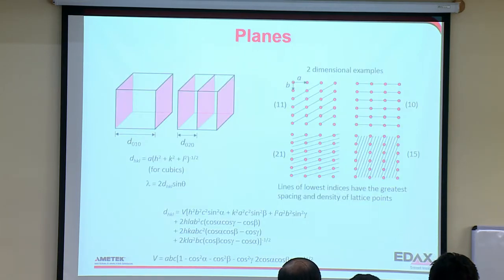So a note about planes. D-spacing is somewhat important in EBSD, although not critical. And just to show you an example, as we go to higher indices, the atoms are actually farther apart on the planes. And so the planes of lowest indices have the greatest spacing and density of lattice points. These are just two-dimensional examples. The spacing is defined by this big equation, which takes into account the lattice parameters and the symmetry in a sense.